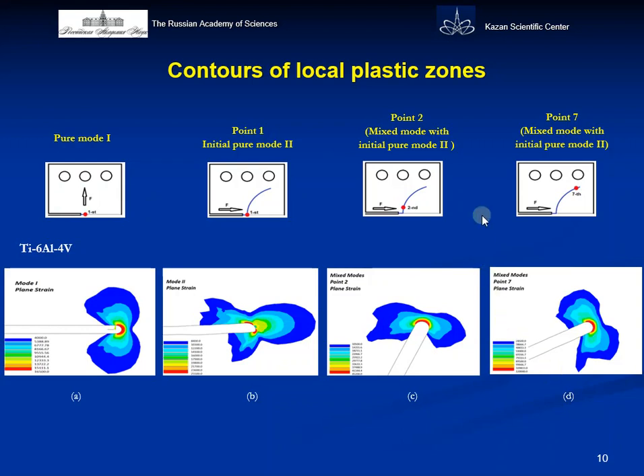A clear demonstration of the redistribution process of non-linear deformation is provided by the contours of local plastic zones at the crack-tip, shown on the next slide as an example for titanium alloy. The plots are shown for applied mode 1 and mode 2 with a material length parameter of 5 micrometers. For pure mode 1, the plasticity zone is symmetric with respect to the plane of the initial crack, while for pure mode 2 this zone is asymmetric. For pure mode 2 loading, one side of the crack-tip is dominated by tensile stresses, while the other side is dominated by shear. At point 2 of the crack path, after the formation of a kink crack, plasticity zones with small asymmetry are observed, indicative of mixed-mode fracture.